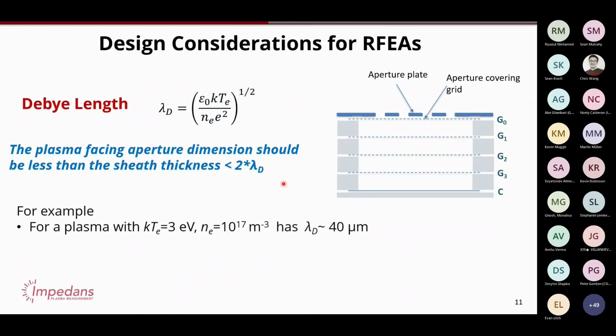So what are the other critical design considerations? One thing is, in order to get good quality data, you have to make sure that no plasma gets inside the sensor. You don't want the plasma forming inside. You want the plasma outside and only measure the ions that are coming towards the substrate surface. The way that works is there's this property of a plasma called the Debye length, and it's based on the electron temperature and the electron density.